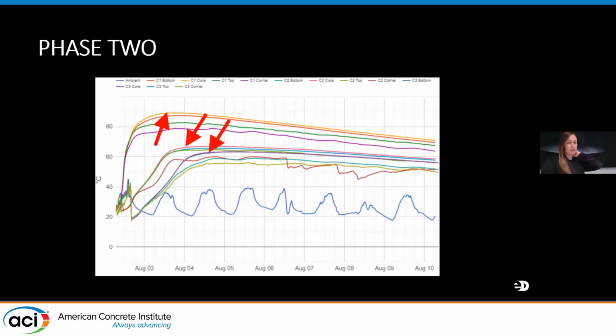As expected, the heat of hydration of the control mix quickly developed over a short period of time, peaking at basically 90 degrees Celsius. That's high. I mean, our max is typically 70 degrees Celsius. For the project, it was actually 65 degrees Celsius for the walls, whereas the two 70% slag mixtures were significantly cooler, peaking at max temps of 66 and 63.